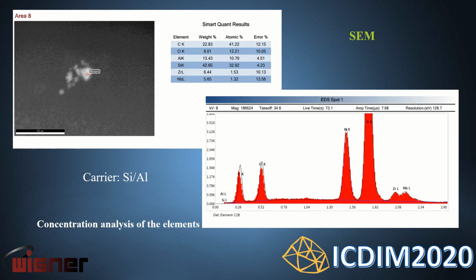The concentration analysis of the elements were also carried out by scanning electron microscope. In this case, a thicker layer of the sample was used. In the spectrum, we can see the material of the carrier, the niobium from the sample, and the zirconium from the crucible and the balls. Their amounts were comparable to the concentration of niobium. This limits the application, although the particle size was appropriate.